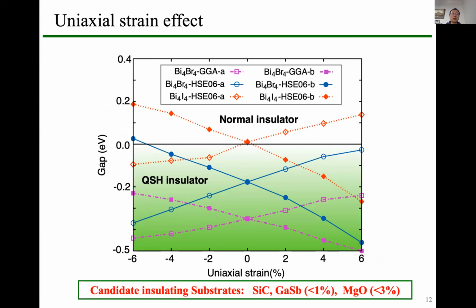So we also calculate their topological properties under pressure. According to theoretical calculations, the topological non-trivial phase of single-layer bismuth bromide can survive a rather large range of strains, from -6 to 6%. The interesting thing is that single-layer bismuth iodide is near the boundary for the phase transition from quantum spin Hall insulator to normal insulator. So if we apply some pressure on this material, it might be possible to observe the topological phase transition.